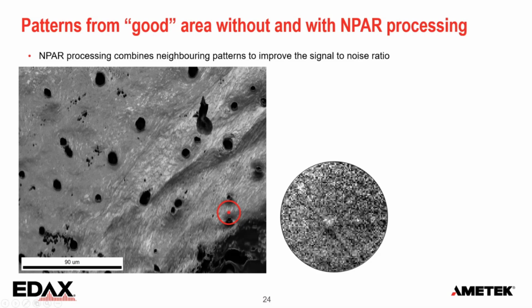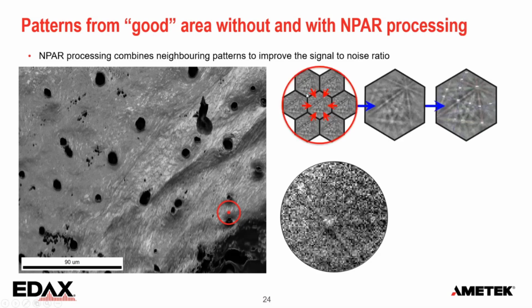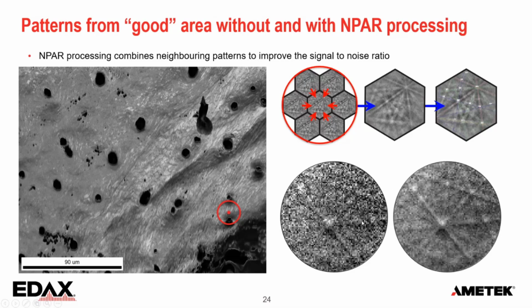What that does is it's like a moving average. We go for a single point, we get a pattern, and then we take the 6 pixels around it on the hexagonal scanning grid that we normally use, and we average those. So we are working with a pattern that is 7 times averaged, and then we can index it. And that brings us from this original pattern to this optimized pattern with improved signal-to-noise ratio.